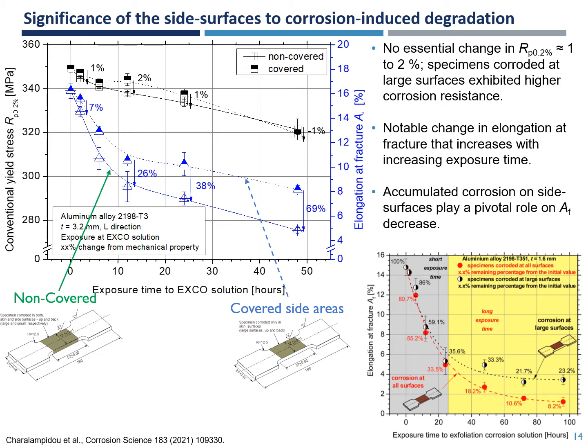The significance of the side surfaces to corrosion-induced degradation was investigated through a comparison of the tensile mechanical properties between the specimens covered in its side surfaces and the specimens non-covered. No essential change in conventional yield stress, shown with the black curves, was noticed between the non-covered and covered specimens. However, the covered specimens exhibited high corrosion resistance. A notable change in elongation fracture between the non-covered and covered specimens was noticed that increases with increasing exposure time.